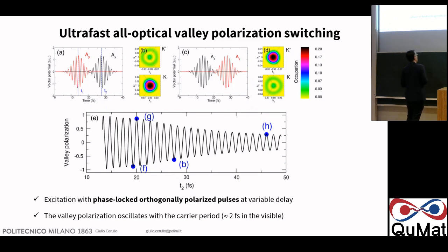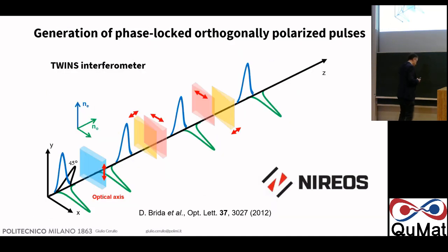In this case, 2 femtoseconds in the visible. And also using sequences of phase-locked pulses, you can switch on and off the valley polarization. Now, it is not easy to make these perpendicularly polarized pulses with such an interferometric stability. You need a really stable interferometer. But we have a trick.